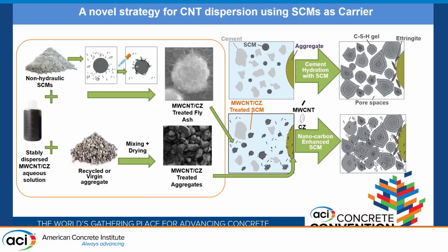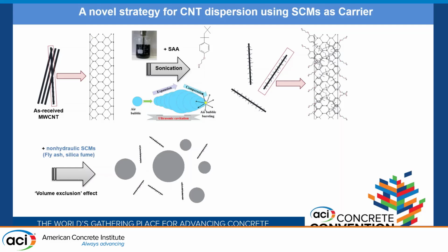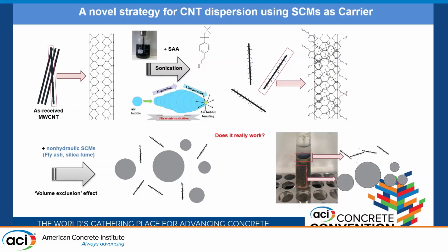So one of the thoughts is, if we use SCM in conjunction with the dispersant, can we use the SCM somewhat as a carrier to deliver the nanoparticles in the cementitious system? We started that experimentation by simply mixing SCMs with the slurry. We tried fly ash, and both fly ash and silica fume together. In that process, we first followed the sonication with dispersant, a very typical way of dispersing CNTs. And then we added SCMs, in this case both fly ash and silica fume, to produce the slurry. Does it work? Of course not. That's just part of life.